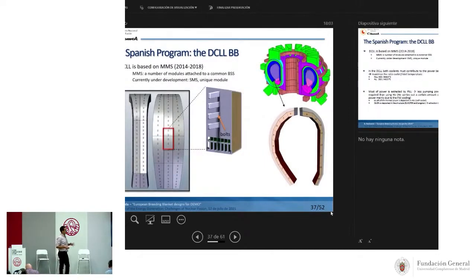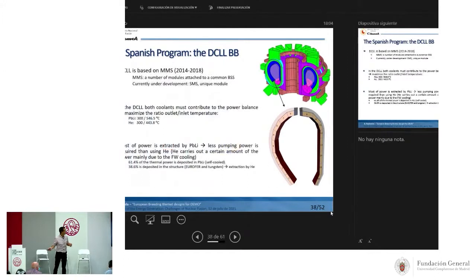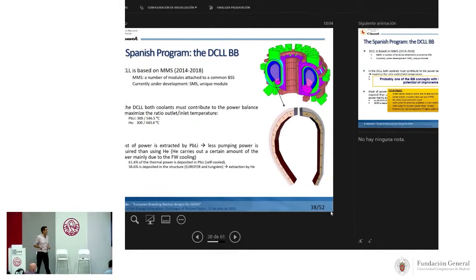The DCLL is based on a multi-module segmentation architecture, which means that we have a number of modules like this, you can see here, attached to a common back supporting structure. We have several modules, and inside each of the modules, I will explain later. As explained, in the DCLL, both coolants must contribute to the power balance, maximizing the ratio between the outlet and the inlet temperatures, but most of the power is extracted by the lead lithium, because this is interesting for the efficiency of the plant, because for pumping the lead lithium we need lower pumping requirements than for pumping helium, for instance.